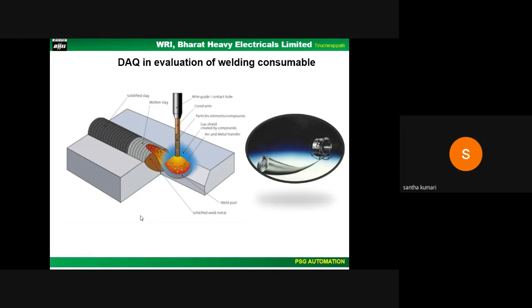Flux core uses a tubular wire that is filled with flux. The arc is initiated between the continuous wire electrode and the workpiece. The flux which is contained within the core of the tubular electrode melts during the welding and shields the weld pool from the atmosphere. Direct current electrode positive is normally employed in flux core arc welding. These requirements of flux core wire manufacturing are clean.